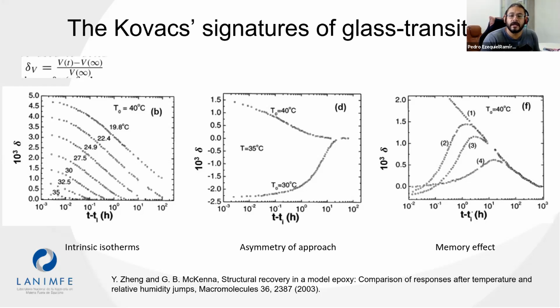The intrinsic isotherms consist of measuring delta after a sudden temperature change. They demonstrate a non-exponential decay of the structural recovery and the shift in the equilibration time during an isothermal relaxation as the temperature of annealing approaches the nominal glass transition temperature. The asymmetry of approach consists of following two routes to the final state, one above the final temperature and another below it. The experiment shows the nonlinearity of the structural recovery.